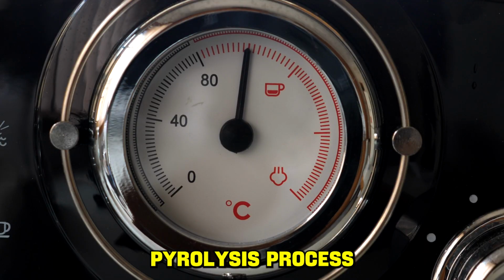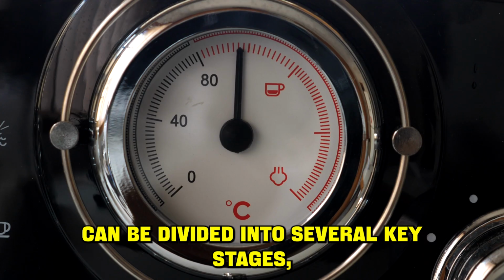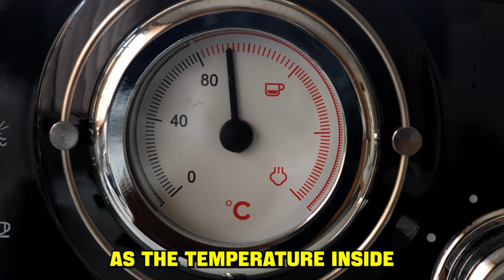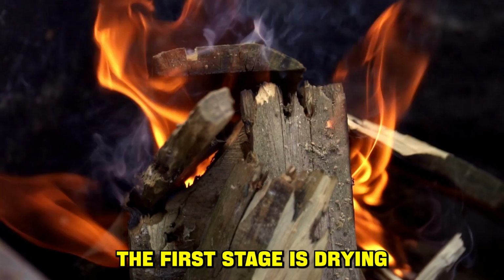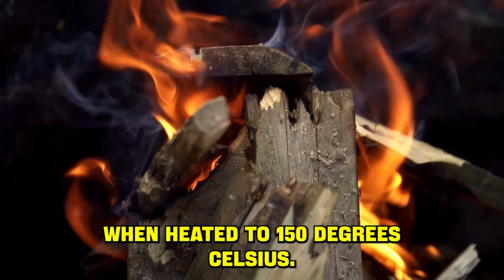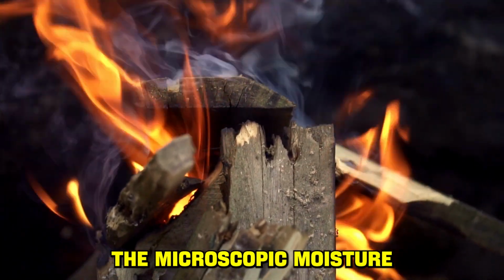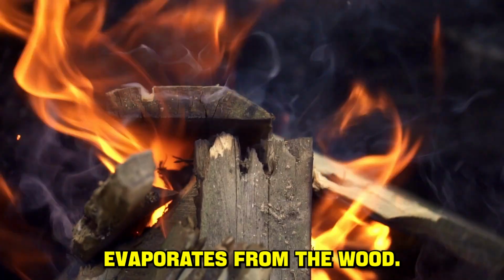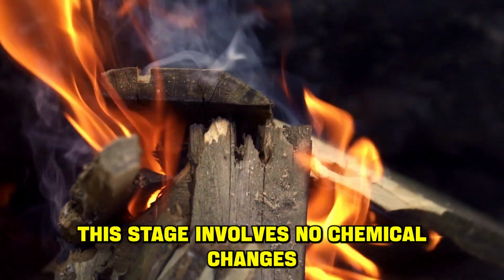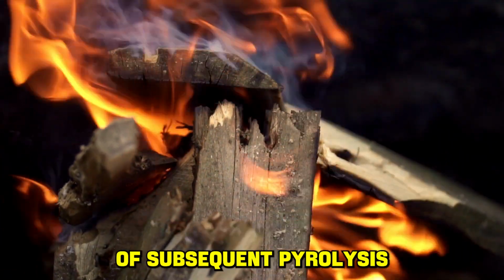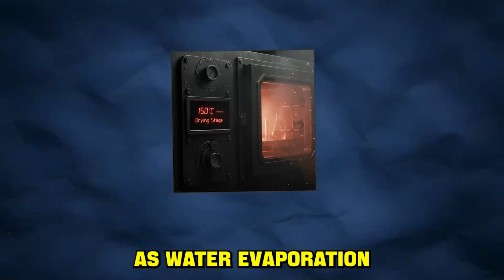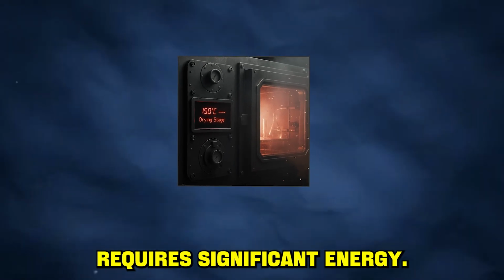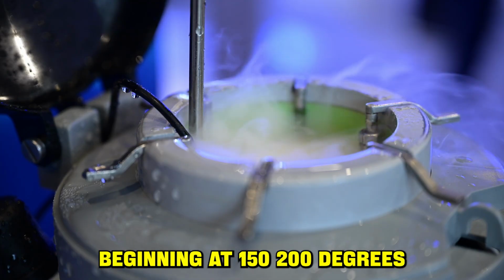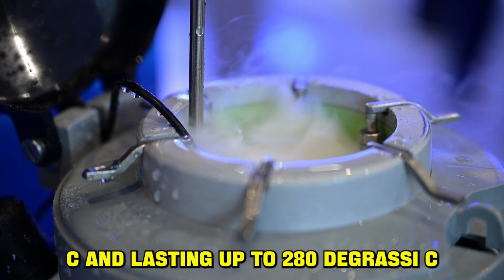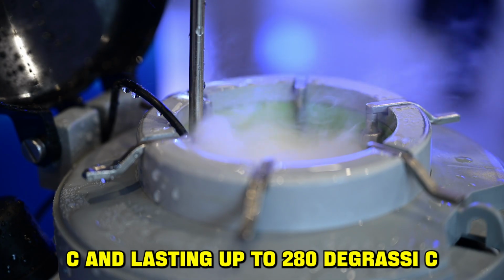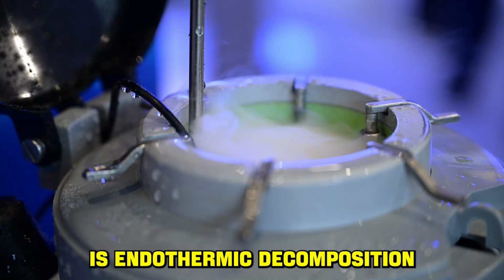The wood pyrolysis process can be divided into several key stages, which occur as the temperature inside the loaded wood increases. The first stage is drying. When heated to 150 degrees Celsius, the hygroscopic moisture evaporates from the wood. This stage involves no chemical changes, but is critical for the effectiveness of subsequent pyrolysis, as water evaporation requires significant energy.